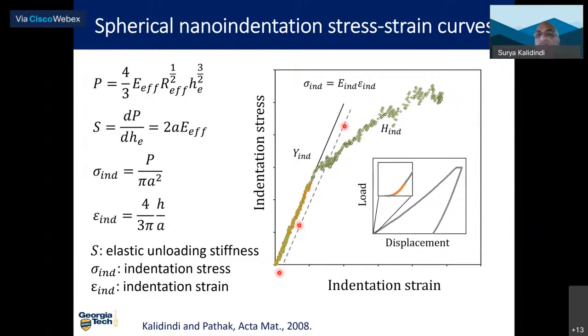So now you can do an offset yield strength definition. These are indentation parameters. This is an indentation modulus. You can define the slope of this line as indentation modulus. You can define this as indentation yield strength. So you can basically do this very fast. Once you learn how to do that, you can do this very fast.